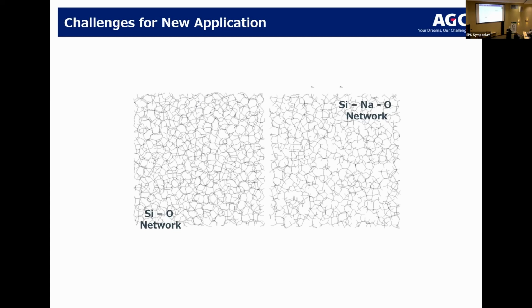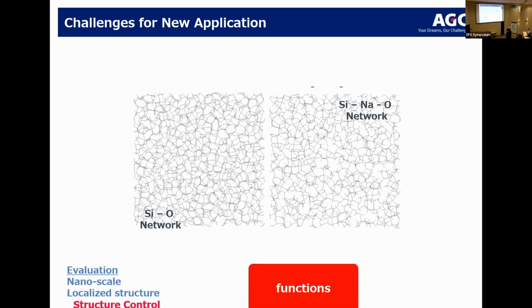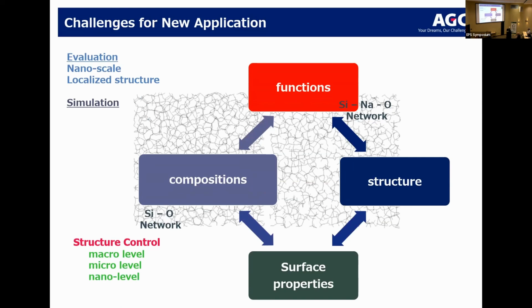sodium-containing glass. I've heard some of the silicon guys who say, "Oh yeah, it'd be a great material if it's just silicon." But silicon's lossy. Silica glass not containing alkali systems don't perturb the signal. Sodium-containing glasses do perturb the signal, so we don't use many sodium-containing glasses in high-frequency applications because of the attenuation of the signal. We can adjust the glasses by function, compositions, surface properties.